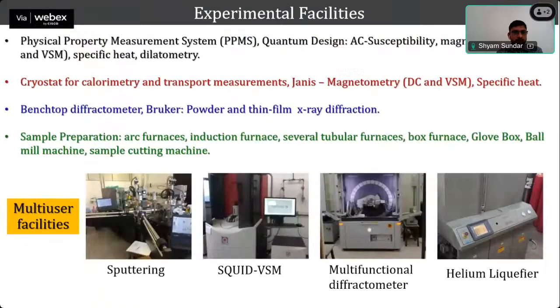And in terms of the experimental facility, we have a physical property measurement system called PPMS from Quantum Design, where we can measure the AC susceptibility, DC magnetization using VSM, specific heat, and dilatometry, which is thermal expansion or magnetostriction, down to 2 Kelvin and up to 9 Tesla magnetic field.